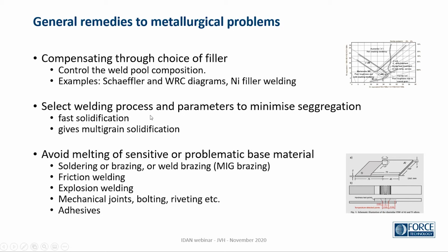We could also, the reason why laser has been researched, is that if we can select a process and welding parameters to minimize segregation, then we would have fewer problems. The fast solidification works against having sulfur or whatever is causing problems concentrate in the solidification. We have more grains and more grain boundaries to distribute the impurities on.